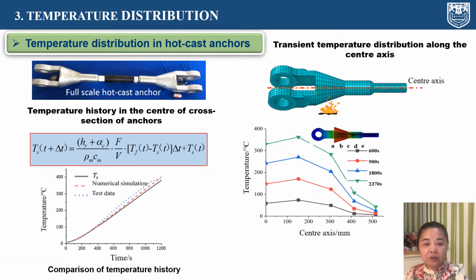Experiments are conducted to determine the specific heat and thermal conductivity of filling materials, such as zinc-copper alloy for hot cast anchors, and the mixture of epoxy resin and steel shot for cold cast anchors. A formula to calculate the transient temperature distribution of fillers in hot cast anchors is derived based on the lumped capacitance equilibrium, which depends on the thermal properties of the filler material. The temperature along the central axis of anchors is non-linear, as shown in the picture above.